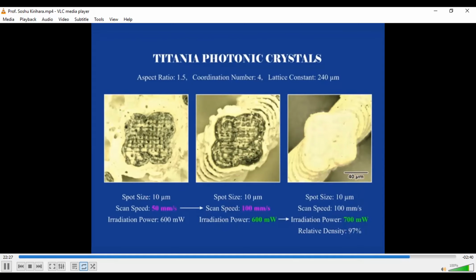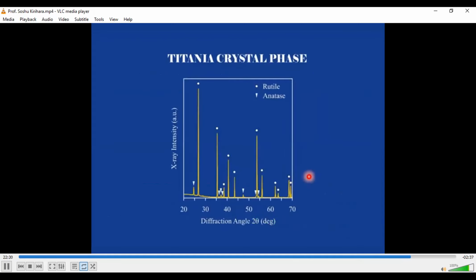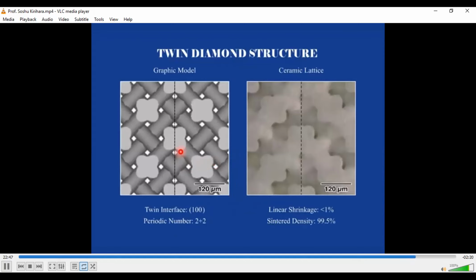We want to try heat treatment. So, in this case, after heat treatment, the lattice crystal structure was rutile structure, with a higher dielectric constant. Okay, and by using directional fabrication and the ultraviolet laser lithography process, we can create twin diamond structures. Okay, here is the real structure, and these dotted lines are the twin defect. Here the right side and the left side have a mirror symmetric diamond lattice. Here is a plane defect.